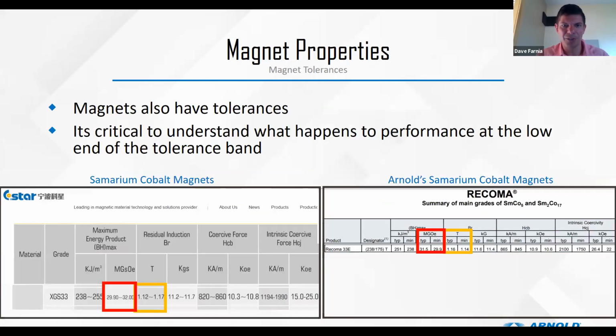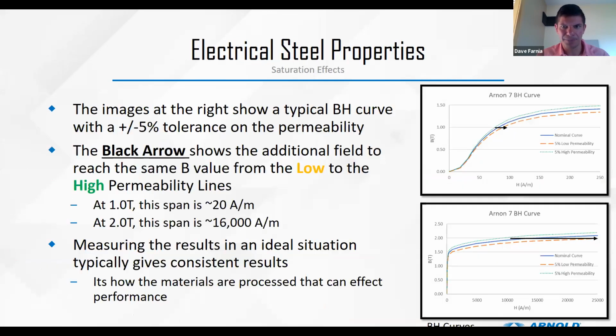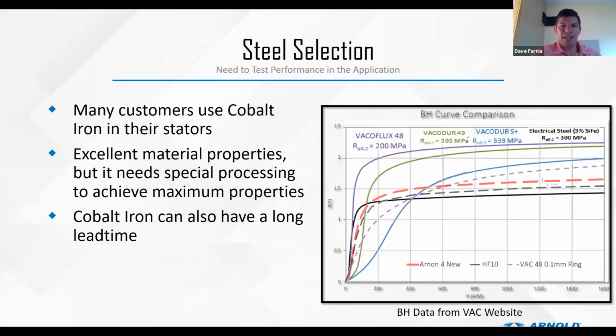It gets a little more difficult for electrical steels. For the electrical steels, M19 is pretty robust. The data sheets that you would get for M19 are going to be fairly representative of what you would get in either a prototype or production environment. The thinner materials need a little bit further processing. Stacking them can be difficult, and if we get to extremely thin materials, we have to work with lamination vendors that are good at stacking very thin materials.